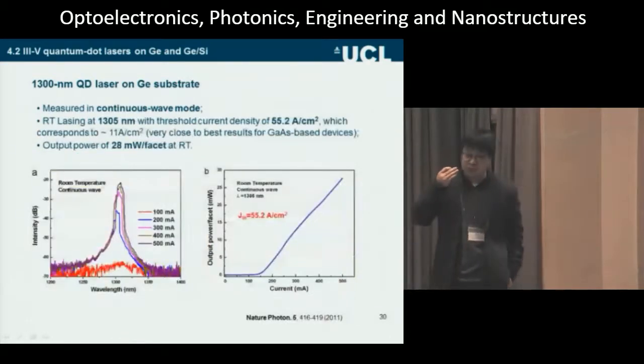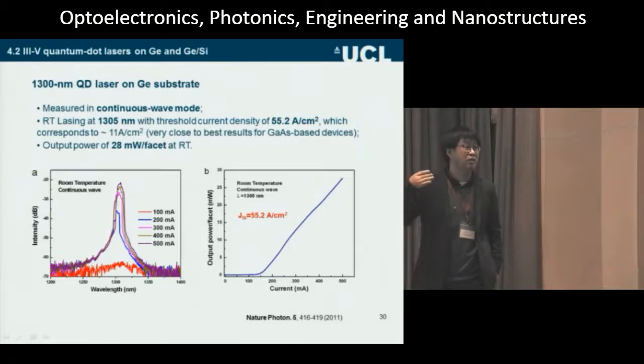Actually, the result is very surprising. It's the first time we get a CW operation laser around 1.3 micron. So it's exactly the second window of telecom communication. And also the threshold is very low. It's as low as the record result from gallium arsenide. And also the power is reasonable.